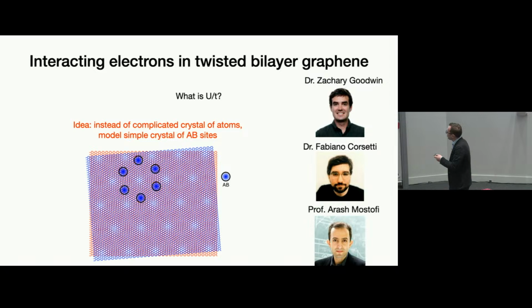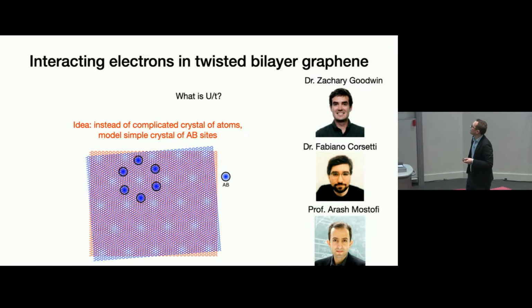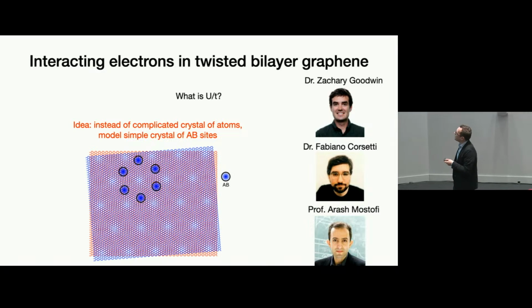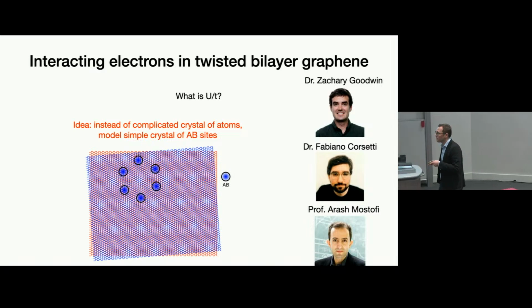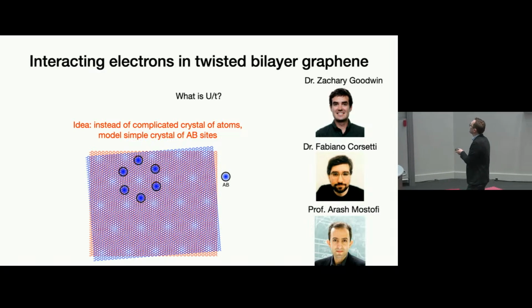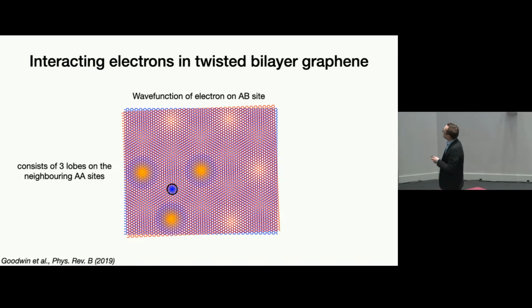Now, it turns out it's rather difficult to calculate this because of this complicated Moiré lattice of the atoms. So instead of dealing with this very complicated Moiré lattice, our idea was maybe we can deal with the simpler crystal of the AB sites instead. So to calculate the repulsion of this simpler crystal, we had to know what the wave functions were of these AB sites. Now this is a bit of a weird question, but using a technique called Wannier functions, we were able to calculate the wave function of an electron on the AB site. These are these orange colored distributions here.